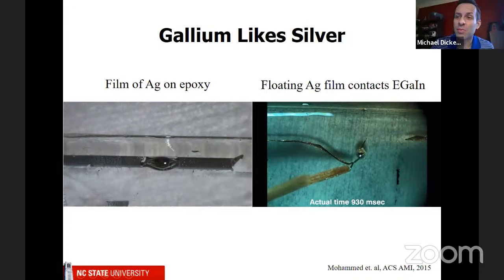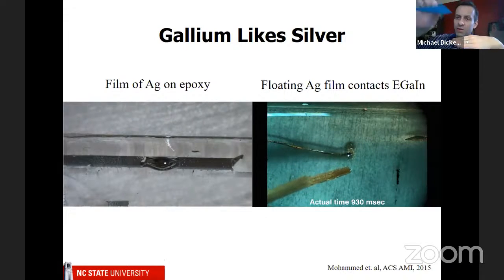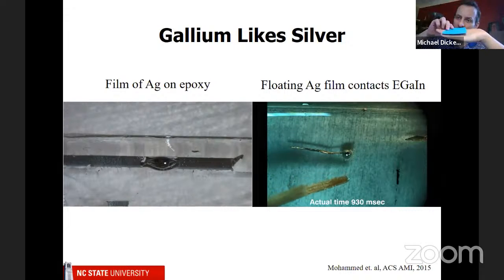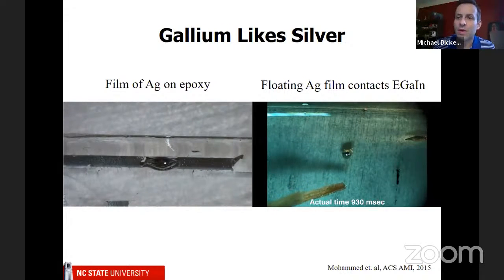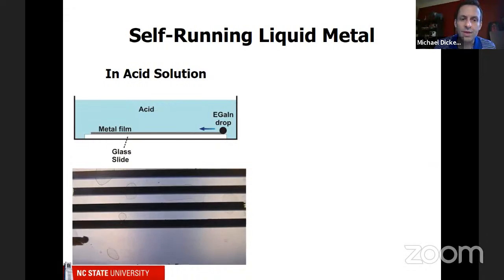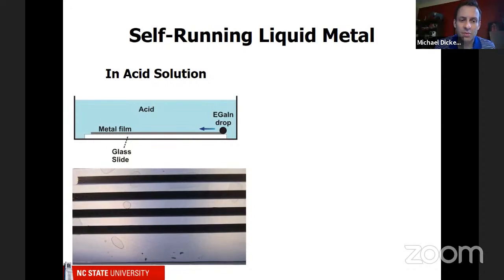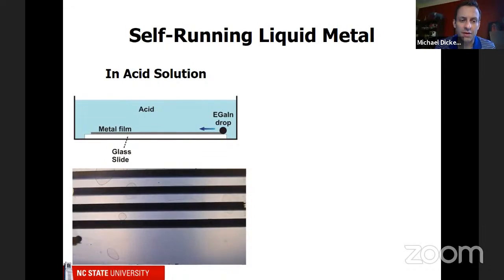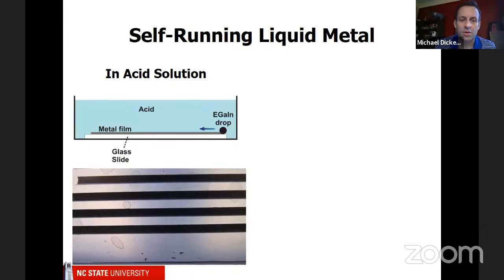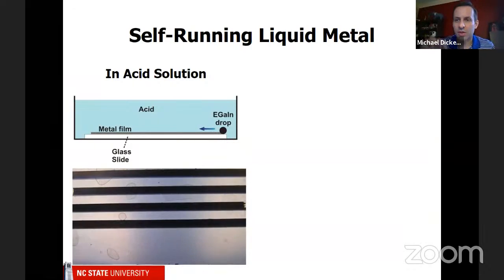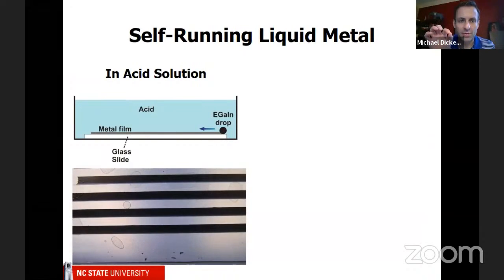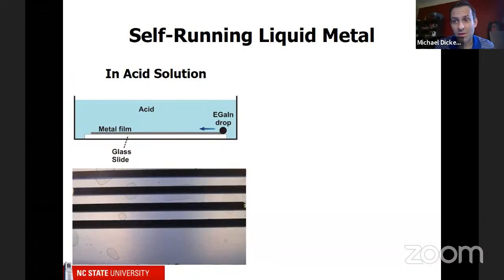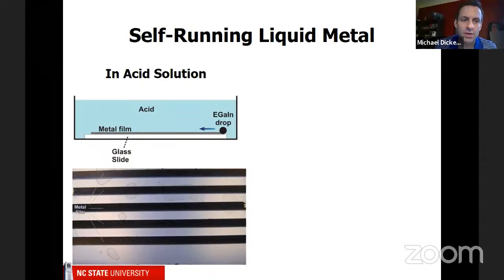So then we thought, well, what if we put a film that's just loosely adhered? So imagine this is your film, and you just loosely adhere it to the surface. So there's a little bit of force, but not much. So we did that, and you'll see that the liquid metal moves along that film. All that's happening is we're just putting a droplet of liquid metal in the presence of acid so that there's no oxide, and it just zips along this film. So here we do it in acid.